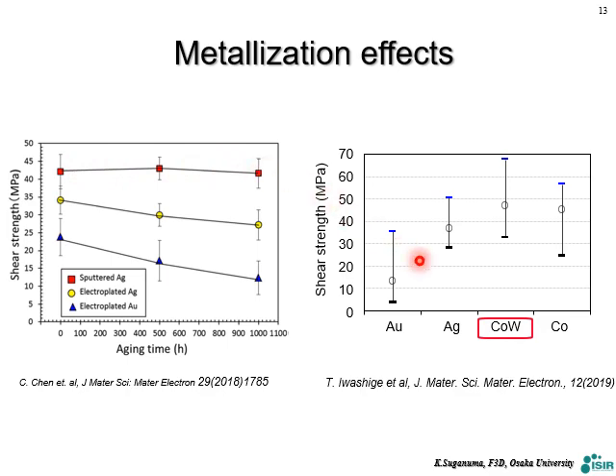But lately we found a much better choice. Sputtering becomes somewhat expensive. So among the plating and many other materials we tested, we found some types of plating material, like cobalt tungsten or cobalt, that are even better than silver, like this. This shows the initial strength. So this is one of the best choices we tested, and not so expensive like silver or gold.